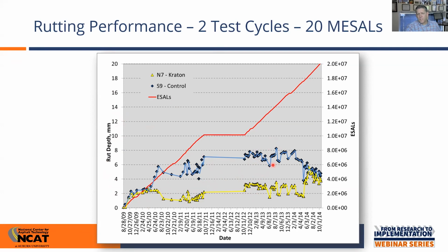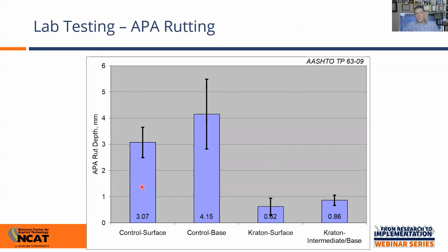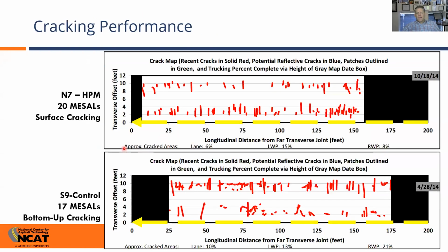So very good rutting performance from both of those, which wasn't a surprise when we ran these through the APA and did our rut testing on our specimens. We saw that it had improved rutting performance in this laboratory test. So that wasn't a surprise to us. When we look at cracking, this is interesting. We did see cracking in both of the test sections, but I need to point out that these 2 plots were selected because they look very similar in terms of how much cracking we see. The control got to this point at 17 million ESALs, and the high polymer mix was at 20 million ESALs. So it outperformed the control, number one.